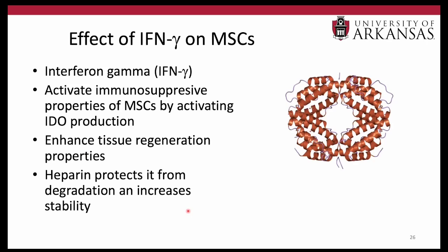All right, so we wanted to study the effect of this cytokine, interferon gamma. And interferon gamma is a fascinating cytokine that activates the immunosuppressive properties of MSCs. And one way that it does that is by activating the production of this molecule known as IDO. It's been also shown to enhance the regeneration of tissues. And what's nice about IFN is that heparin has been known to protect this cytokine from degradation. It provides stability. So we did cultures for the cells on our coatings in the presence and absence of this cytokine. And then we did a bunch of studies.